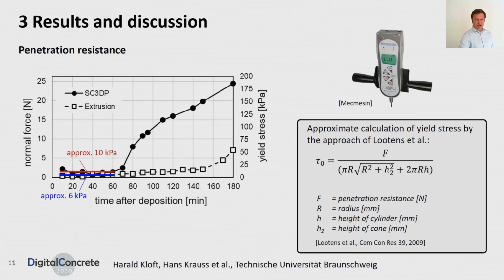We have no clear explanation for the steep increase of yield stress here after 70 minutes in case of shotcrete 3D printing. We are still working on that problem because there is no real reason from the viewpoint of chemical hydration, because hydration really starts only here after 140 minutes significantly. So we are working on that question. But however, we can keep in mind that after those results, the shotcrete 3D printed specimens should be more prone to cold joint formation than the extruded specimens.